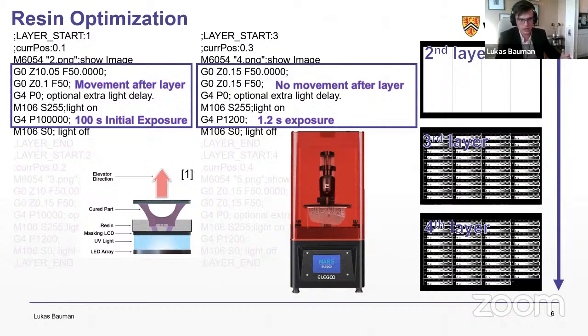So we developed our own exposure test that prints 2 base layers that are totally flat and 50 micrometers thick. And then after that, the 3rd to the 42nd layer are these scales. And every single layer, it removes one of these scales, but instead of raising and lowering every single one of the layers, it stays steady. So you end up getting sequential exposure of each of the scales.